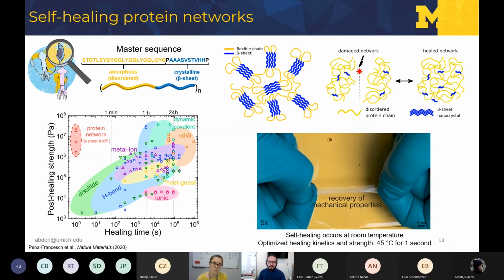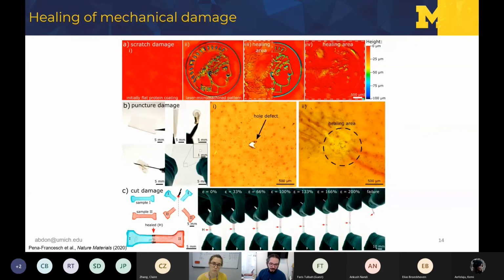So when we saw this, we were very excited, and we wanted to validate this against different types of damage, right? And we tortured our materials basically. So we validated against different types of mechanical damage. For example, we can see here against scratch, we use the protein as a protective film, where we could scratch the surface, exposing the material underneath, but we could recover the surface coverage after a very short healing time.